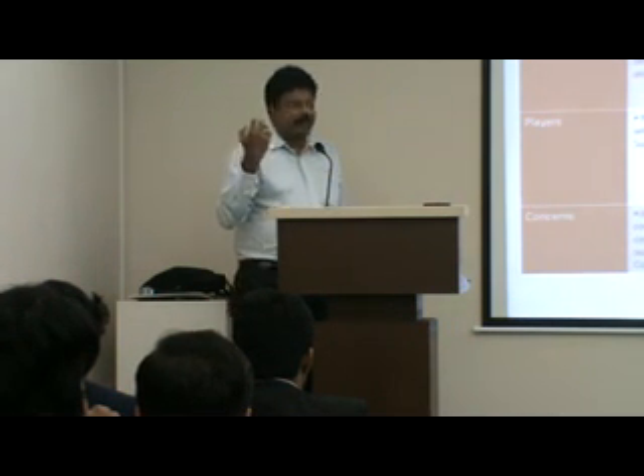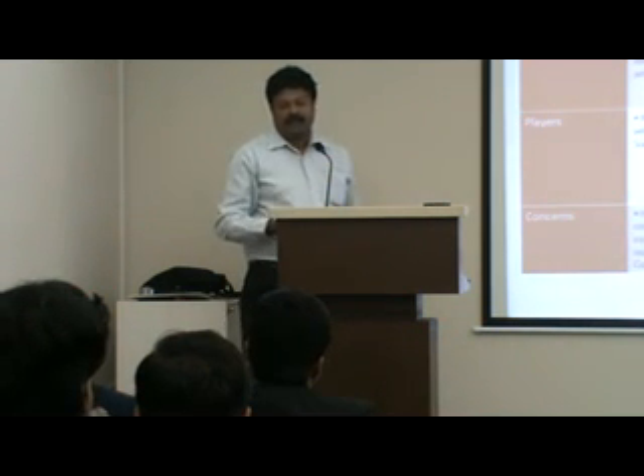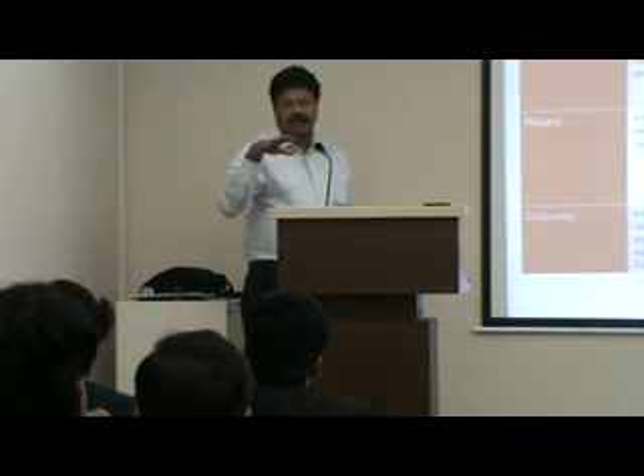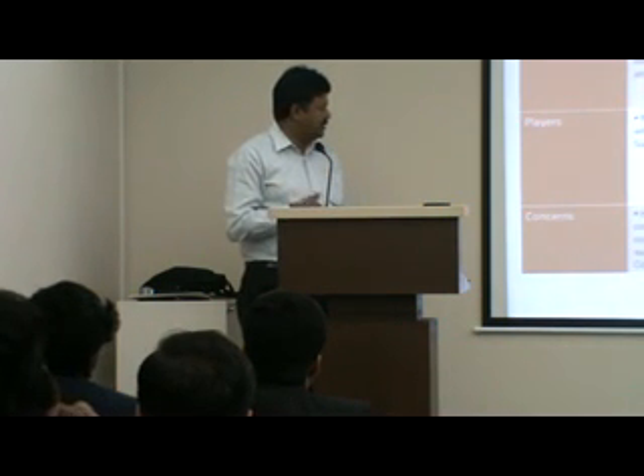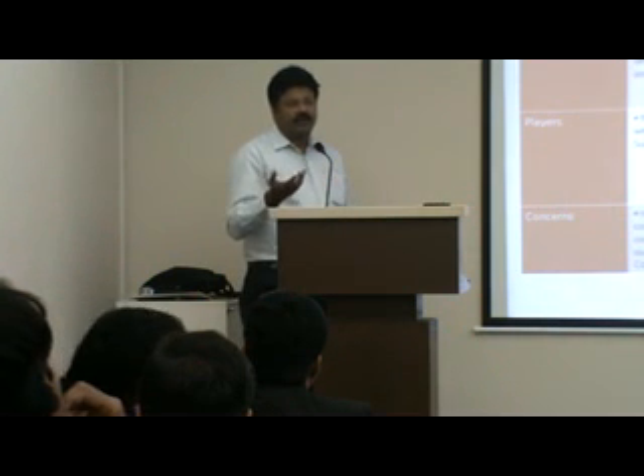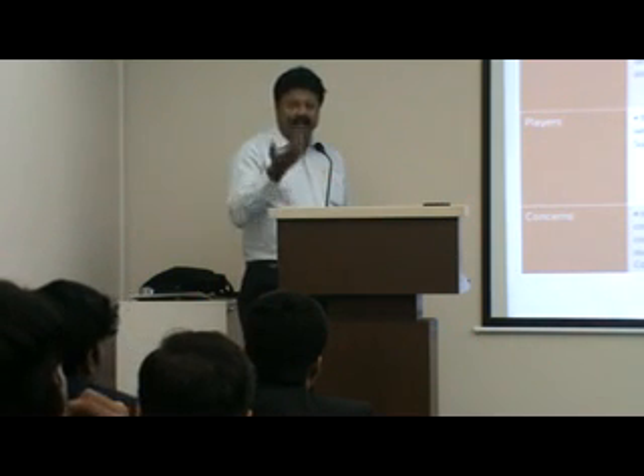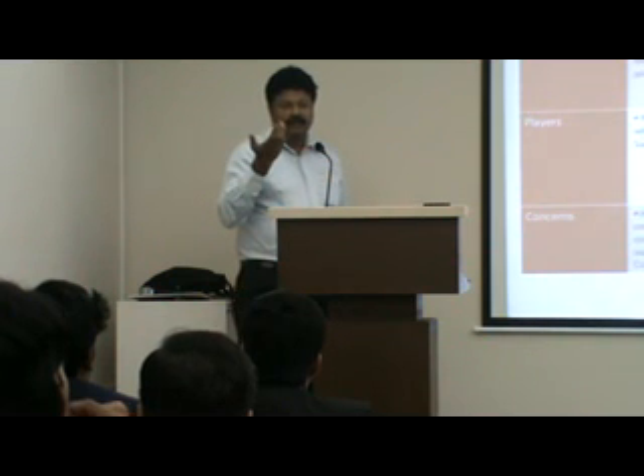Out in Gujarat and Rajasthan, we have sometimes found the actual radiation to exceed that number. Plus, the main problem that happens is temperature. The standard condition temperature is treated as 25 degrees centigrade. That's the level at which the capacity is measured. And typically, your temperatures out in the field would be 40-45 degrees centigrade. And the panels itself will heat up to about 55, 60, 65 degrees centigrade, under 45 degree ambient conditions.